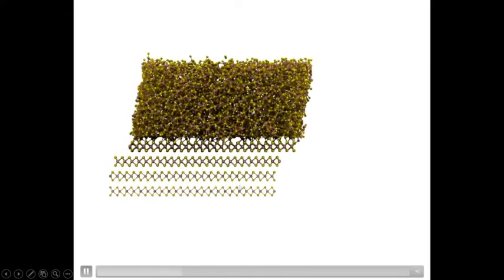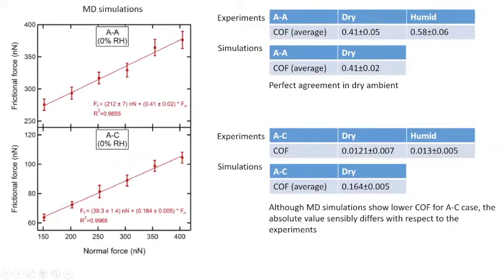So also in the case of the simulation, we can generate the frictional force as a function of the load. And again, we can calculate the coefficient of friction in the case of the simulation for amorphous and amorphous crystal case. In this case, we are only able to do this in dry conditions, so in absence of humidity. And the comparison with respect to the experiments shows that in the case of amorphous coupling, we have a perfect agreement between simulation and experiments. And in the case of amorphous crystal pairing, again, the coefficient of friction is lower with respect to the case of amorphous, even if the difference with respect to the experiments is much higher as well.